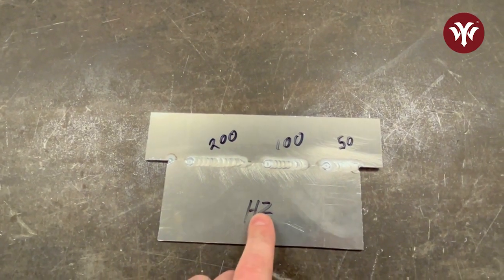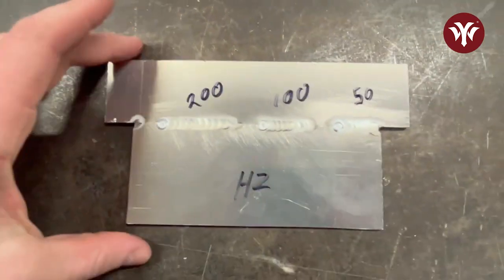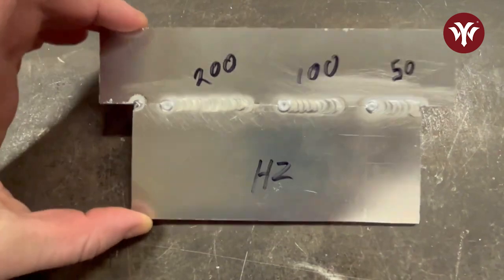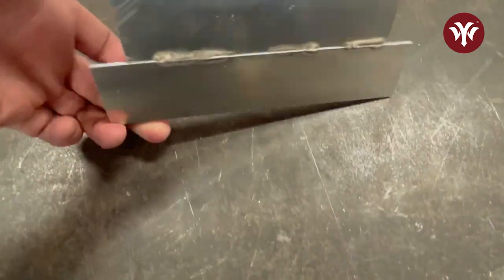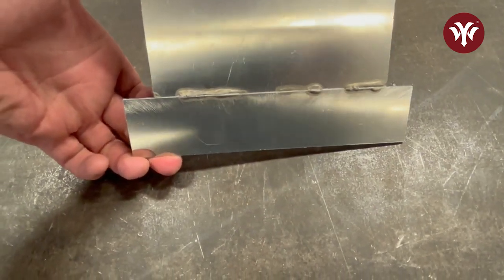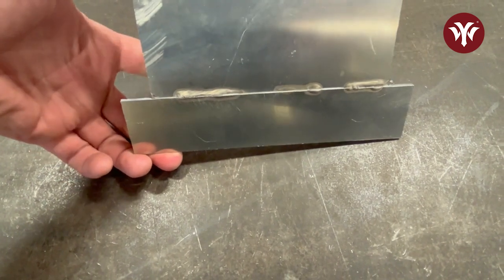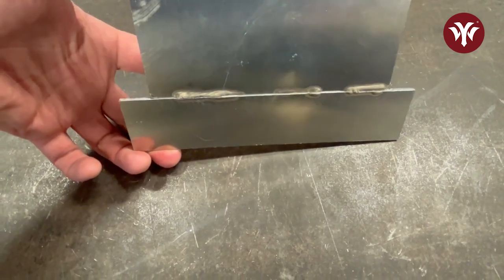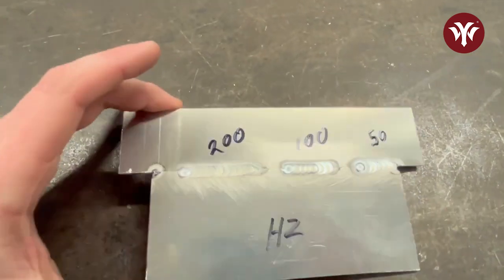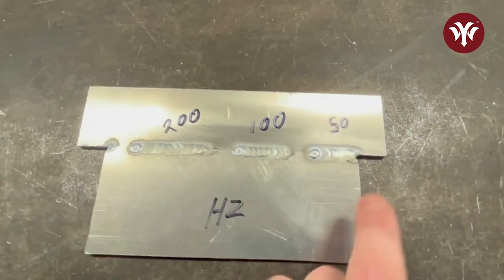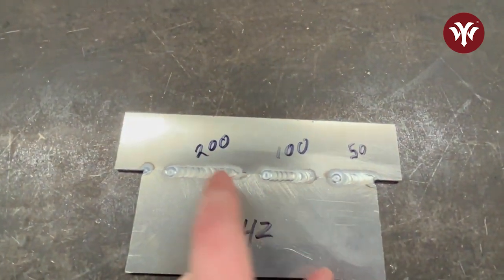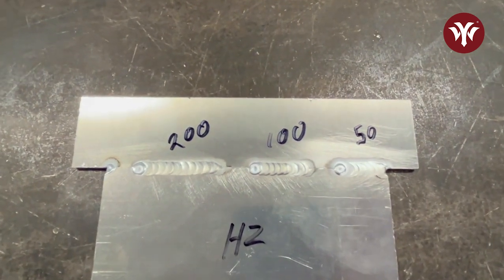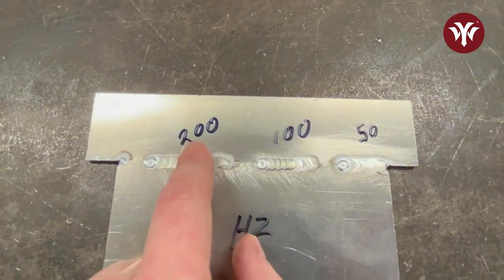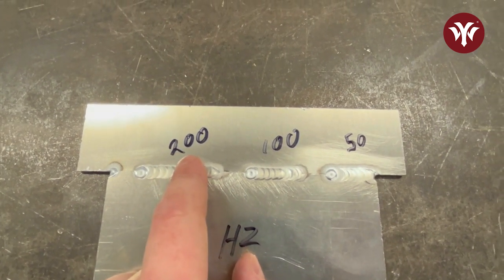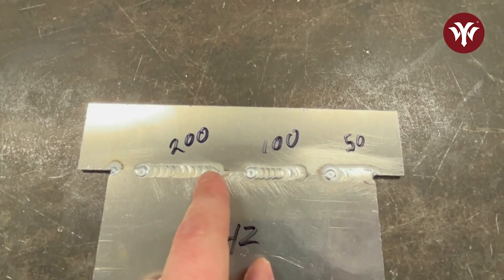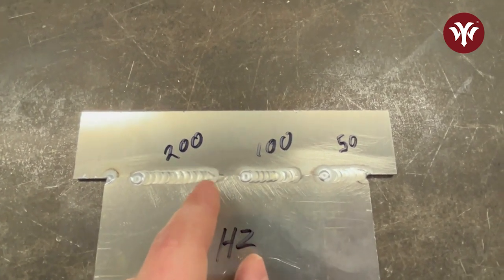Okay, here's the coupon that we were playing with frequency. As I thought, and it's hard to show you here, there's very little difference in the look of these welds. Penetration varied. I wasn't really paying too much attention to that, so I can't really make a comment on penetration versus frequency. But what you could really tell was the sound. 50, 100, and 200 hertz. You could definitely hear the difference in those welds. And my understanding is that as you go to higher frequency, that allows you to weld on thinner materials. You get more cleaning cycles, and it should penetrate a little bit better.